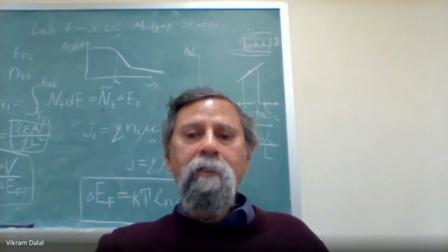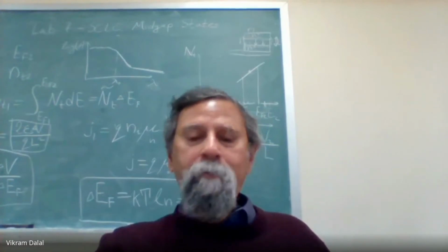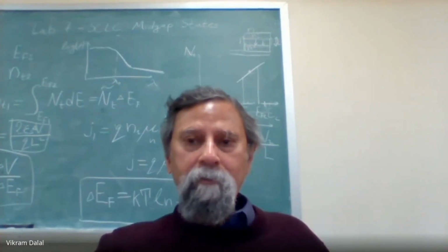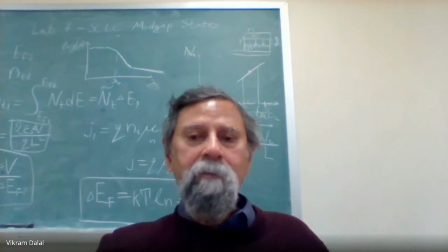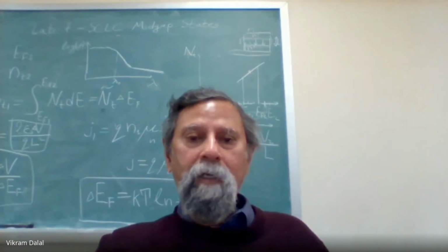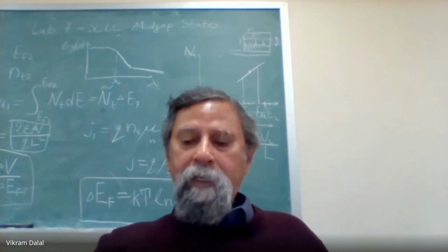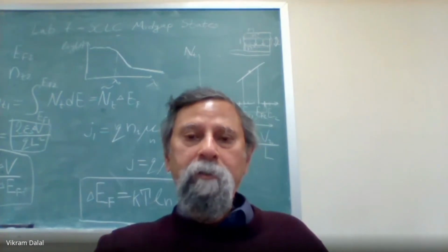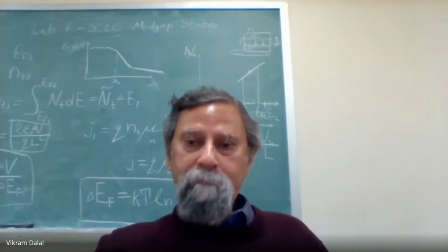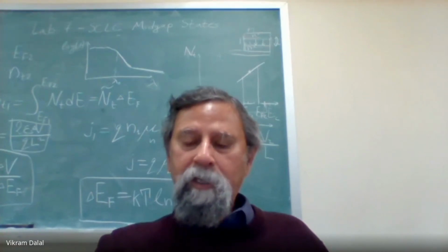And what we are showing here is the exceptional reproducibility of evaporation. I mean, every cell is essentially the same as the other. When we use PTAA, liquid deposited, champion efficiency is about 18.5, 19%. This was done by one of my students from Bangladesh, Istiaq Hossain.